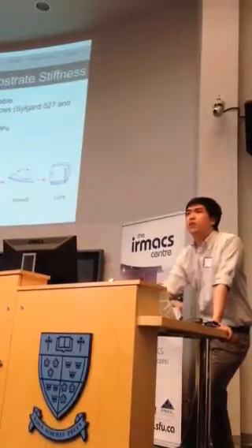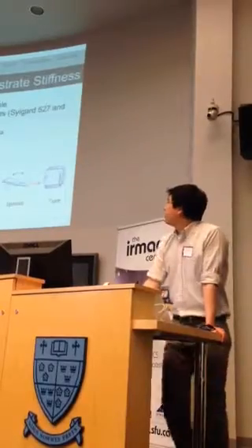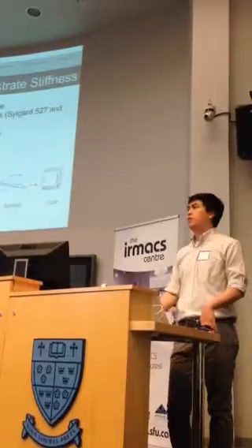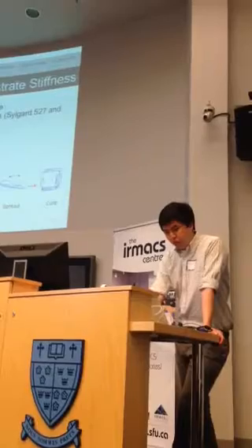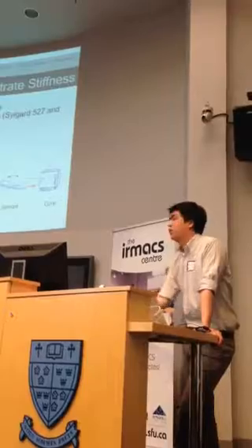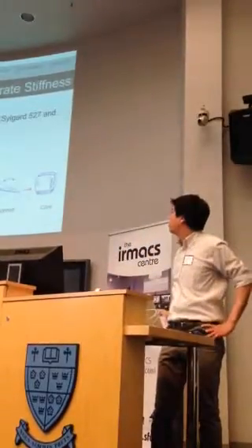So to test our hypothesis, we need a way to vary the stiffness of the substrate on which the stem cells grow. According to a protocol set up by Francesco, this can be done by blending two commercially available polydimethylsiloxane (PDMS) subtypes, Sylgard 527 and Sylgard 184. And you can get a substrate of varying Young's modulus between a soft 5 kilopascals to a fairly stiff 1.72 megapascals.